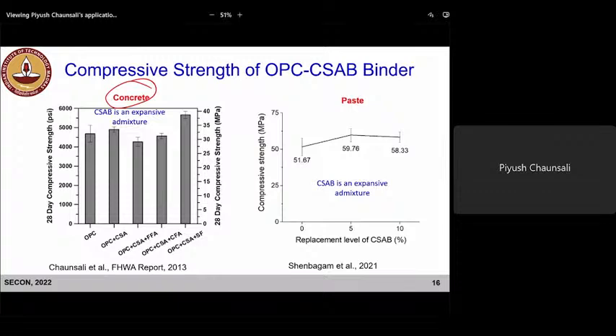CSAB cement can also be used as an expansive admixture, right? As we saw, type K cement is basically an expansive cement where CSAB admixture is used. In that case, you see CSAB cement enhances your strength. When we add CSAB cement to Portland cement, there's some increase in the strength, and obviously you see the effect of other admixtures here. So you don't compromise strength. When we use CSAB as an expansive admixture, in some cases you see an increase also.